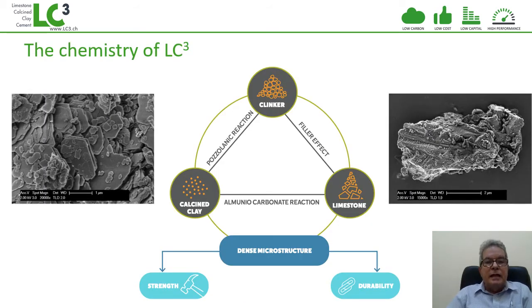A little bit about the chemistry of LC3. So here it's very complex, it's actually a ternary binder. So we have three reactions taking place at the same time. On one side, we have calcined clay, which qualifies as a pozzolan. So there is a pozzolanic reaction between clinker and calcined clay. But also we have limestone, which is finely ground. Therefore, it has a dilution effect. It's the so-called filler effect, meaning it's diluting the clinker phases, it's enhancing the hydration of clinker phases, and it's providing also sites for heterogeneous nucleation of the reaction products.